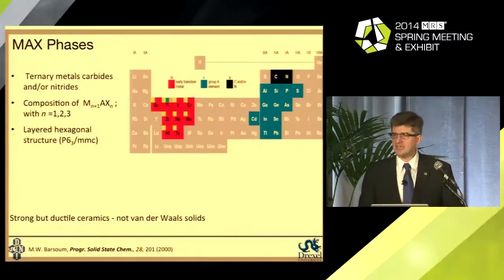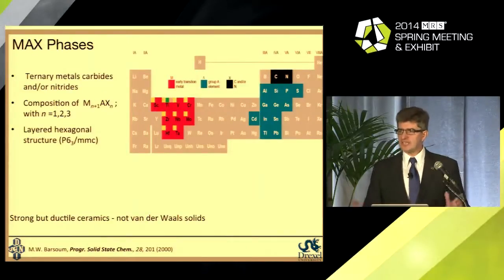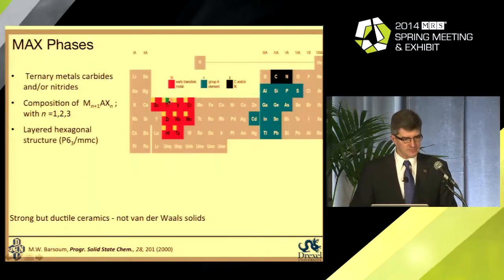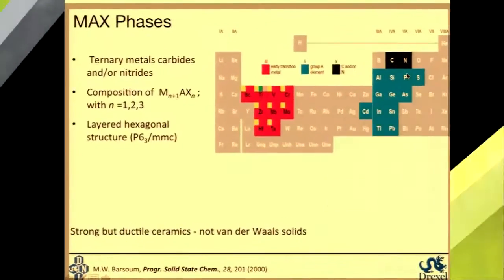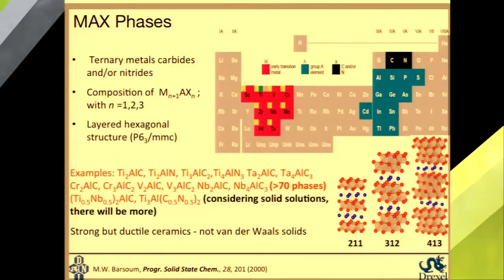So how are they made? Why are they called MXene? We take MAX phases, which are layered transition metal carbides and nitrides, carbonitrides, built of this M element. The A element is one of the elements from this group, and X stands for carbon or nitrogen. This is a very well developed and studied family of ductile ceramic materials. My colleague at Drexel, Professor Michel Barsoum, is really the father of this field.